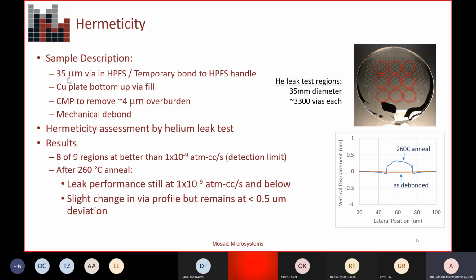But the other aspect of this is we wanted to measure hermeticity. So we annealed these wafers up to 260 degrees C. We did the process I just described: the bottom up fill, CMP to remove the overburden, mechanical debond. Then we did the anneal, and then we measured 9 regions on that wafer for hermetic performance. First we did the gross leak red dye test, and then we did a helium leak test. 8 of the 9 regions had better than 10 to the minus 9 atmospheres cc per second of helium.